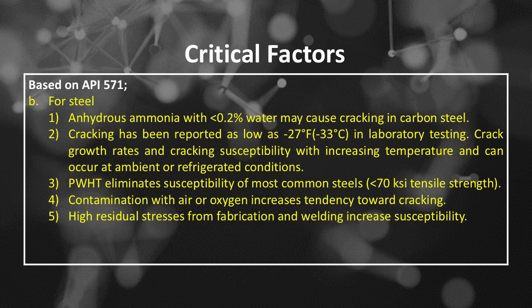Number B, for steel, includes, number 1, anhydrous ammonia with less than 0.2% water may cause cracking in carbon steel. Number 2, cracking has been reported as low as -27 degrees Fahrenheit or -33 degrees Celsius in laboratory testing. Crack growth rates and cracking susceptibility increase with increasing temperature and can occur at ambient or refrigerated conditions. Number 3, PWHT eliminates susceptibility of most common steels less than 70 ksi tensile strength. Number 4, contamination with air or oxygen increases tendency toward cracking. Number 5, high residual stresses from fabrication and welding increase susceptibility.